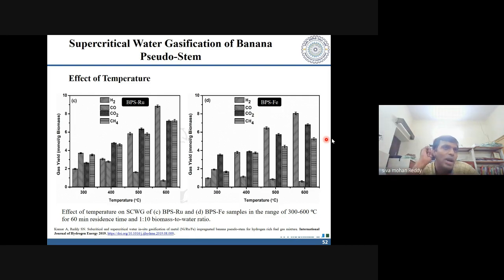One more point that I would like to add is, if you look at the TOCs of these liquid streams that have been formed, the raw biomass has a TOC of nearly 5,500 ppm. For the nickel, it was around 600 or 550 ppm, whereas for ruthenium it was around 1200 ppm, and for iron it was around 1500 ppm. So the TOC of our raw biomass was around 5,500 and it was reduced to almost 600 ppm, which shows that these metals that are formed promote and enhance the gas yields by interacting with the intermediates that are formed during the degradation process.